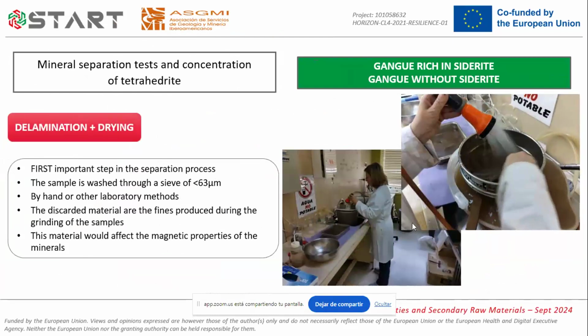As I have explained, the first step, which is common to both kinds of samples, once we have prepared the samples, is the delamination. It is the first step in the separation process. The sample here is washed through a sieve of 63 micrometers. We did it by hand. Here in the photograph, we can see the process. We did it by hand, but there exist other laboratory methods. The discarded material are the fines that were produced during the grinding of the samples, but were not sieved. It is important to eliminate this material, as it would affect the magnetic properties of the rest of the minerals. Finally, the delaminated sample has to be dried in order to carry out the next steps.